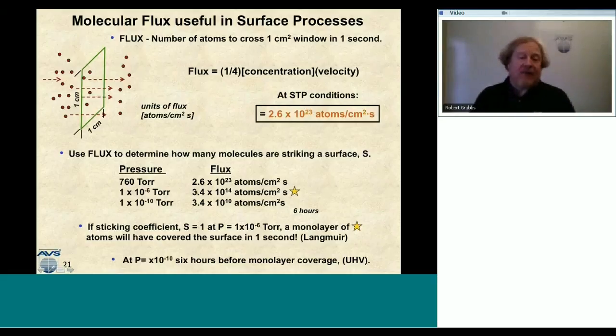Here, look, that flux value of 10 to the 14, 10 to the 15 is about the same order of magnitude as the number of sites on a surface per centimeter squared. This is a very important concept. The number of sites per centimeter squared is about 10 to the 15. The flux of atoms going through a centimeter squared surface at 10 to the minus 6 torr is about 10 to the 14, 10 to the 15. So we can start to relate flux and the number of sites per centimeter squared, and this is going to become invaluable when we start to quantify the ALD surface chemistry.